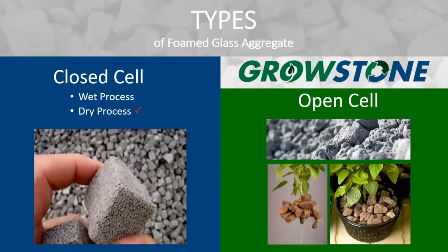And then there's a different type of foam glass that we call open cell material. And, as I said previously, the closed cell is not absorptive. If we switch out our foaming agent, we can make a product where those voids on the interior of the particle are more interconnected. And that's what we refer to as our open cell product. And this is going to be an absorptive material. So you're going to have much higher moisture contents in open cell foam glass. Also, more accessible surface area because of those interconnected voids.